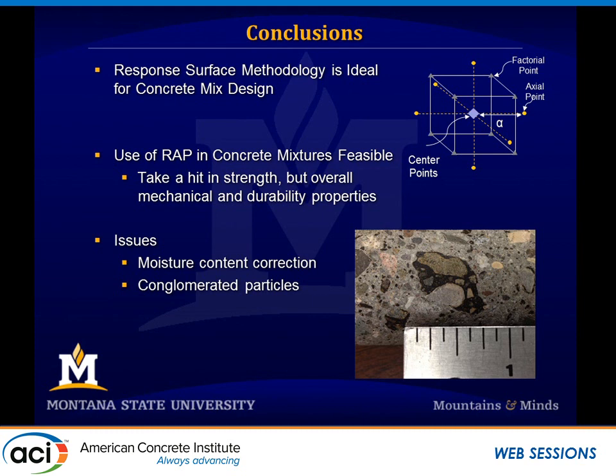And the moisture content correction, how you account for that: the way we accounted for it was by slump adjusting our concrete. From here on out, if this is going to be used more, we have to come up with a better process for doing that. And so our follow-on research is, again, trying to decrease the cement content in these mixes and trying to come up with a better moisture content correction method.